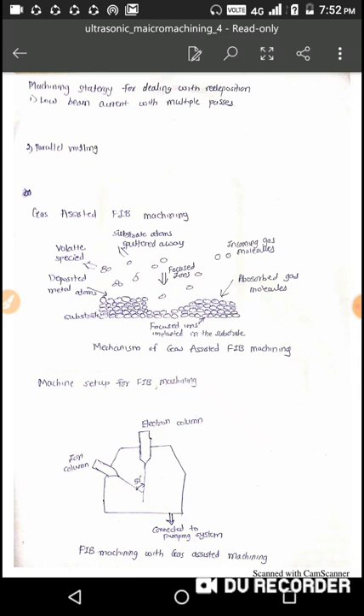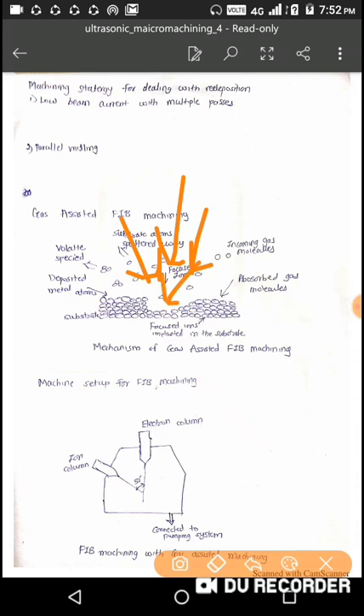The gas molecules, when used, are absorbed on the substrate surface, and when the ions strike the surface, the absorbed gas molecules ionize and chemically react with the substrate surface, which helps in the milling process. So you can see here the gas assisted FIB machining. In all this process, an ion is striking the substrate surface, as I have explained earlier. The only difference is that gases are used. These gases are absorbed into the substrate surface, and when the ions strike the substrate surface, these gases chemically react with the substrate surface and help the milling operation.